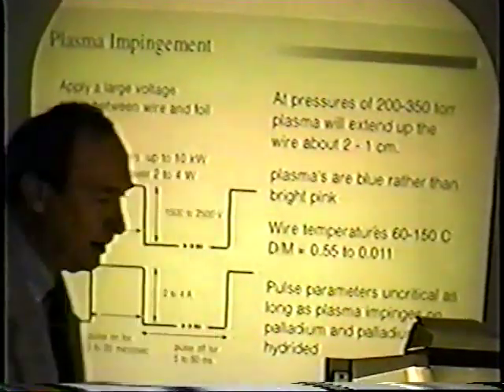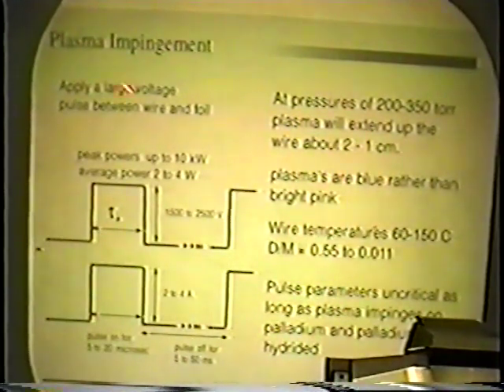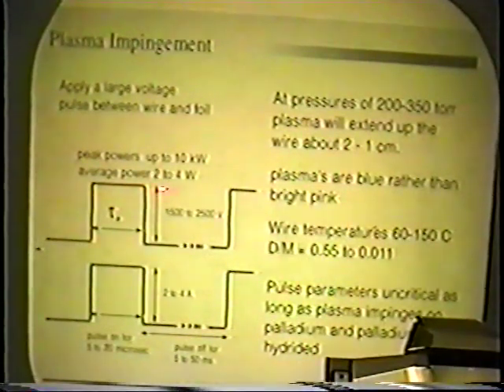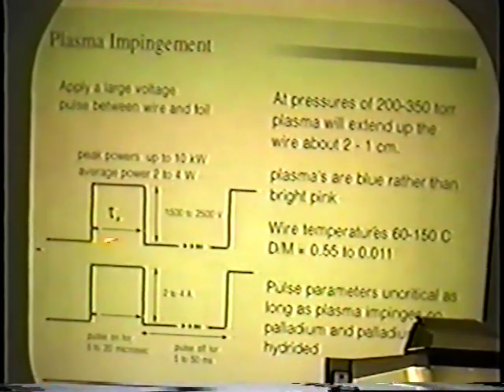Okay, with the plasma impingement method, we just apply a large voltage between a wire and a foil, or a wire and a wire. The peak powers are up to 10 kilowatts, average power 2 to 4 watts, and as I say over here, the pulse parameters are really uncritical as long as the palladium is hydrided. And that's the trick here.